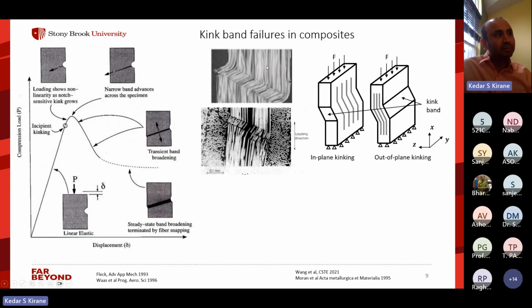So first the fibers will bend a little bit like this, as shown here. And then because the fibers themselves are quite brittle, they will kink. And they will kink at two locations, because if you imagine a fiber bending like this and then coming back to be straight, there are actually two inflection points, if you note. And so then they will kink. So this kind of band will develop, and this is called the fiber kink band. It happens only under compression. And sometimes multiple kink bands can also develop depending on the geometry.